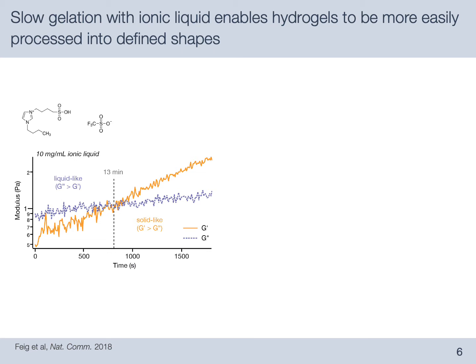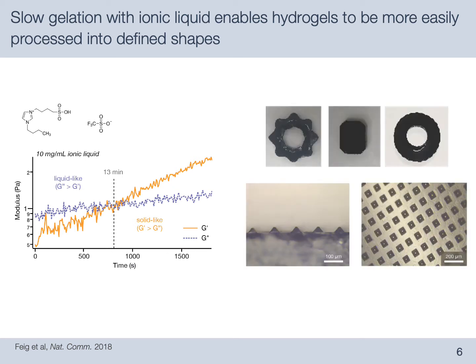We also observed that this ionic liquid resulted in a relatively slow gelation process. We monitored gelation time by mixing PEDOT:PSS with the ionic liquid and measuring its storage and loss moduli on a rheometer. From this experiment, we saw that there was a 13-minute working window during which time the mixture behaves like a liquid, with loss modulus exceeding storage modulus. This gives us ample time to pour gel precursors into molds so that we can form arbitrary shapes, including these small pyramid structures shown here.